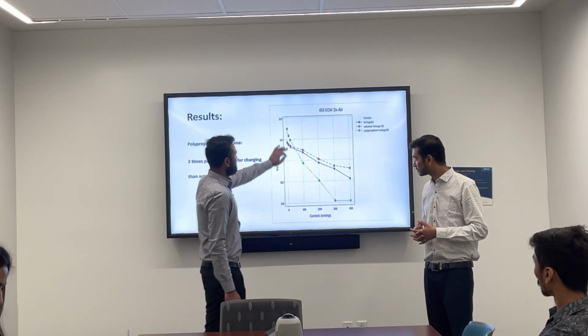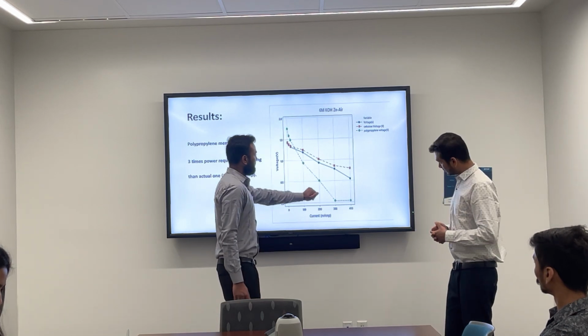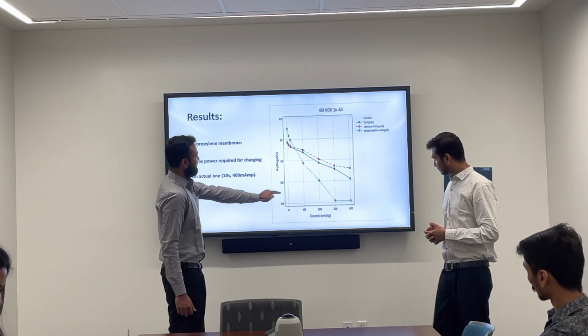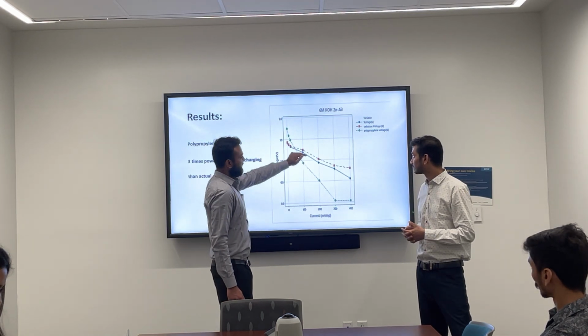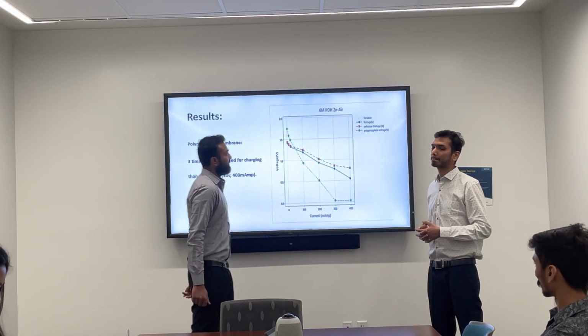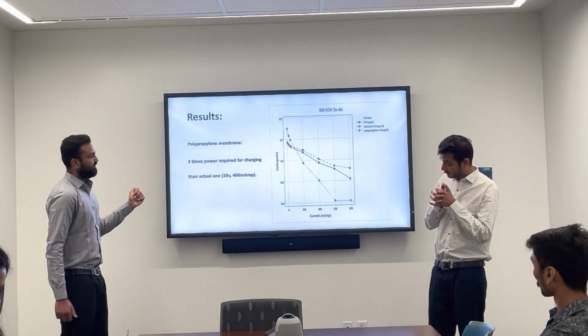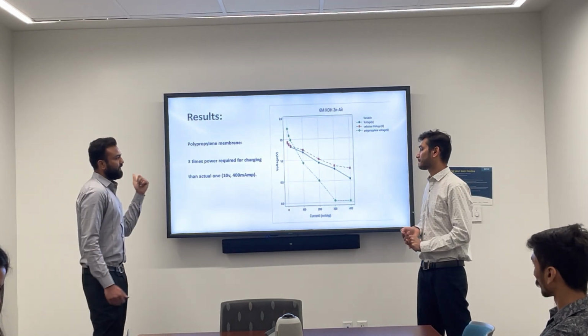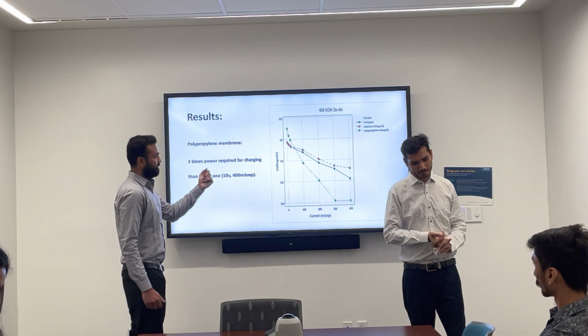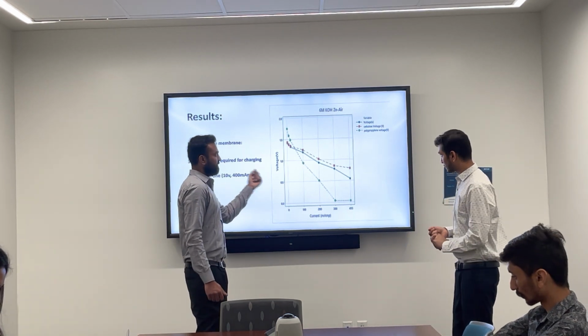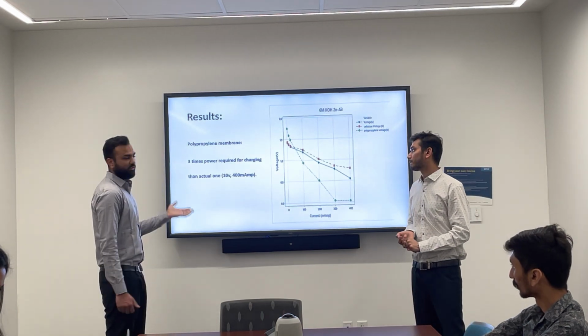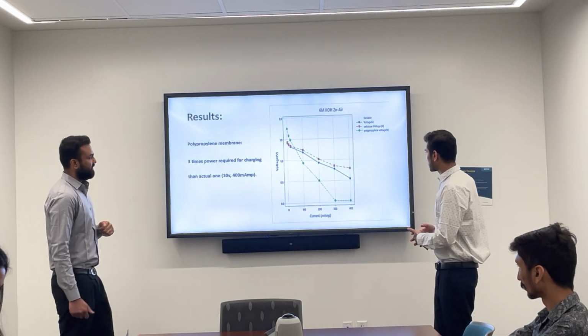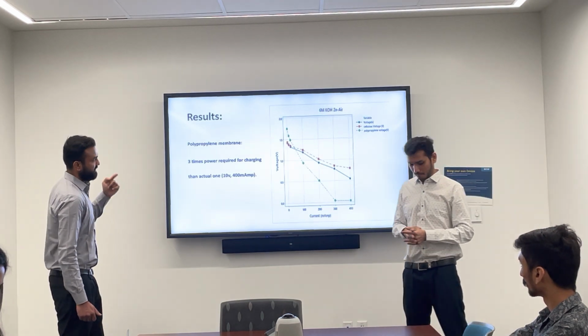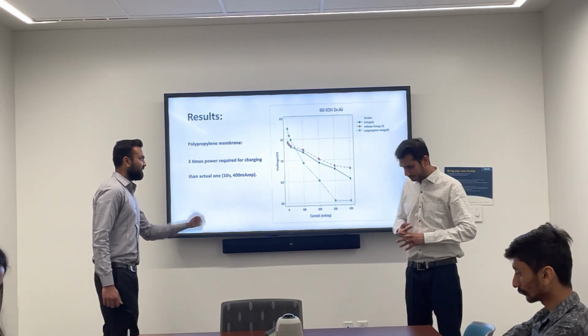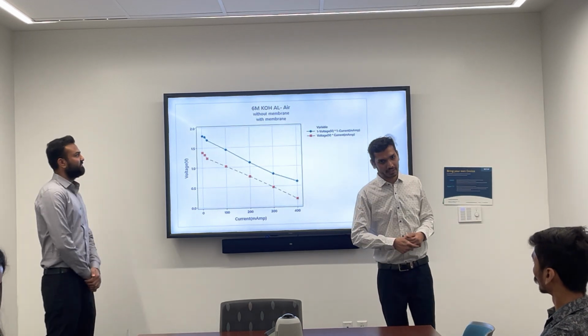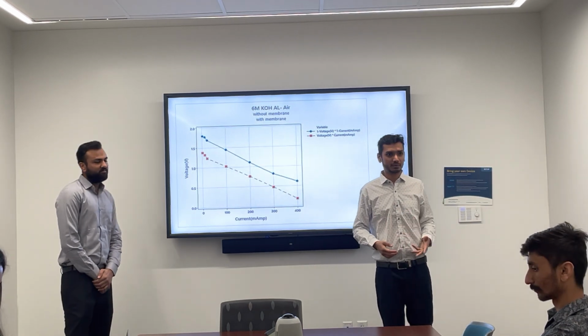Here you can clearly see that when we use the polypropylene membrane, the voltage drops immediately, while in the case of cellulose, it performs better. So we concluded that when we use the cellulose membrane, the battery performs better. It gives a better lifetime compared to without a membrane and with the polypropylene membrane. For further testing, we did not go with the polypropylene membrane. We just tested without membrane and with the cellulose membrane. So here, as Vishal said, we are not using the polypropylene membrane for the aluminum plate.